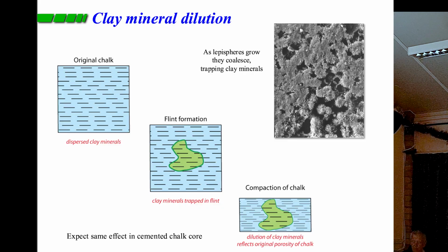They will actually grow within the chalk, which has got a little bit of clay minerals. It's only about 1 or 2% of chalk is clay minerals, but those clay minerals are preserved within the flint. What I can then do is compact the chalk around it, so I finish up with a lower concentration of clay minerals in the flint compared with the chalk. So all I need to do is go and analyse the amount of clay minerals in the flint compared with the surrounding chalk.